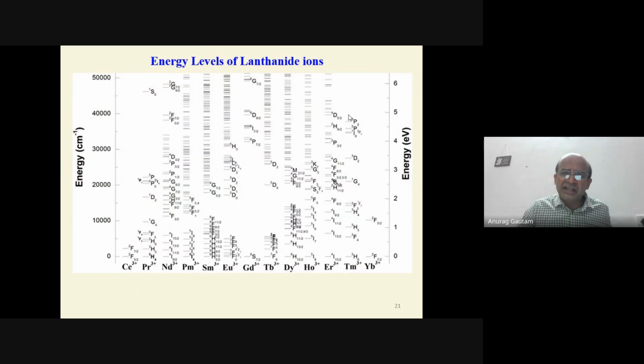And this energy diagram is well known from the literature, showing how the emission comes. We can see emission from these, like gadolinium has this wide energy gap. We see emission, but it is still lacking. The best emitters are erbium and thulium. So this is thulium, you can see the fixed energy levels here. Erbium is also an emitter. Dysprosium is not a very good emitter because this is a continuum type structure, not much gap. Same for gadolinium also, but gadolinium does have some emission.